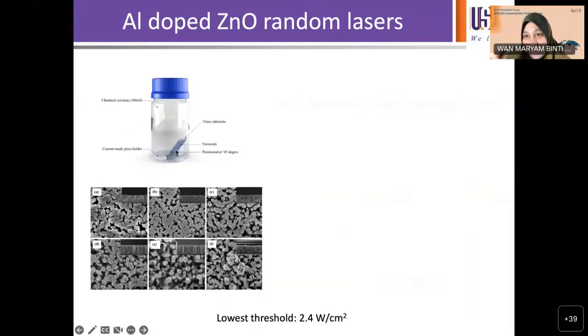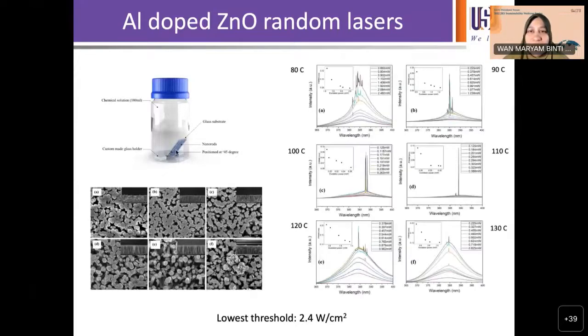So we fix the concentration, and then we vary the temperature, and we observe that with the different temperatures, we actually see different amounts of aluminium, different amounts of doping. From that, we see that at a certain temperature, the lasing is very good. At certain temperatures, the lasing is not so good. Okay, so the lowest threshold was in the sample at 110 degrees Celsius, and this actually had the highest doping. So the highest doping gave the lowest threshold.